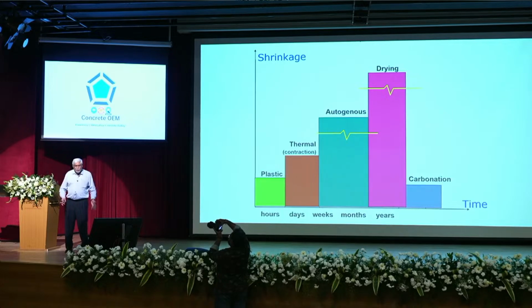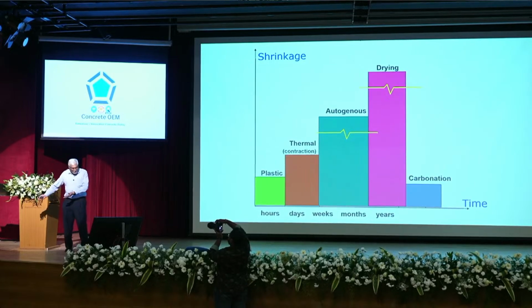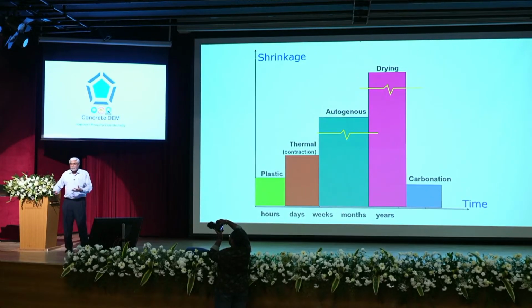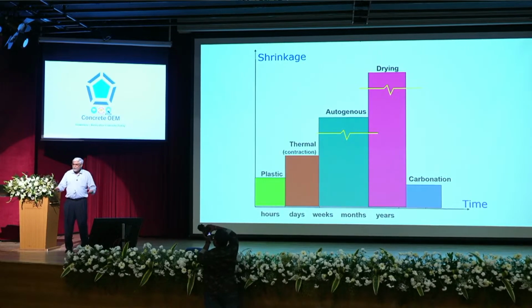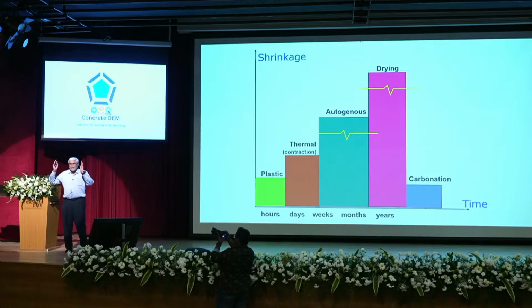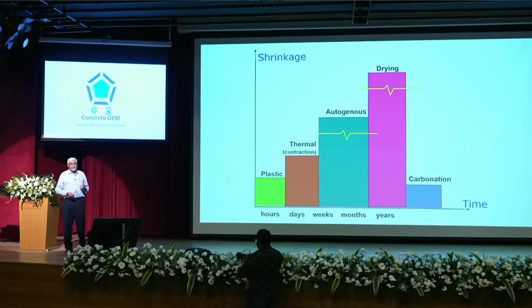If they told you, I just concreted it and there is a crack, plastic shrinkage. If it has happened over a couple of days, 1 week, demolded, cracking, thermal shrinkage. Diaphragm wall is cracking after several weeks, then it is autogenous shrinkage. Okay? So this is something that we should start thinking about. If there is a crack and the structure is not yet loaded, ask, when did you see the crack?